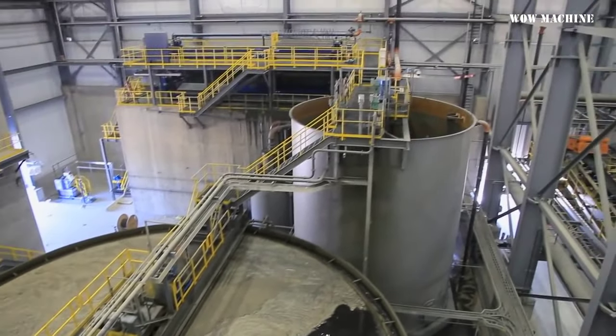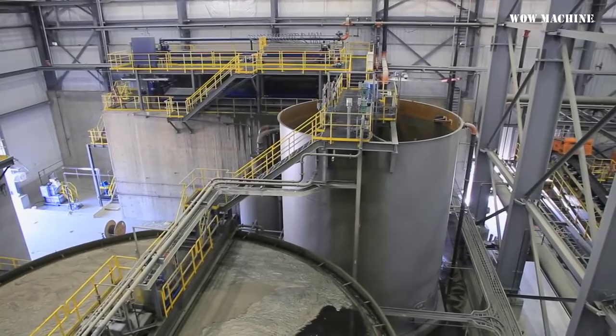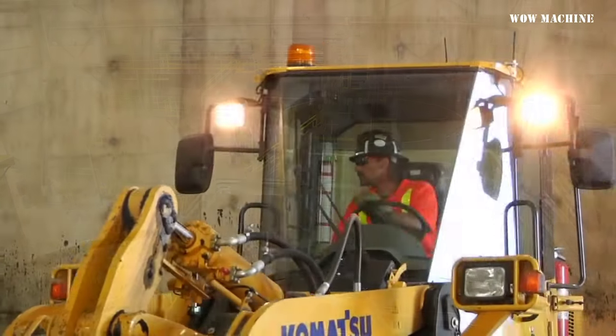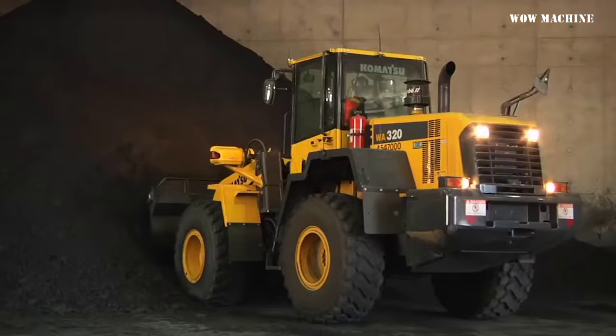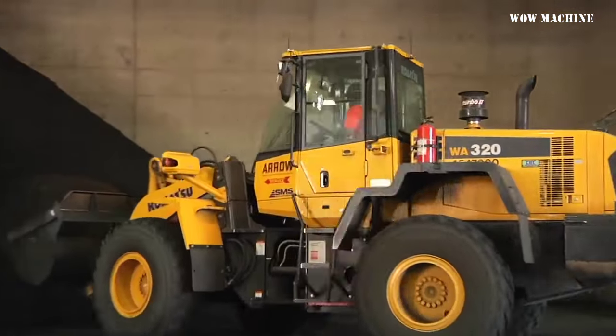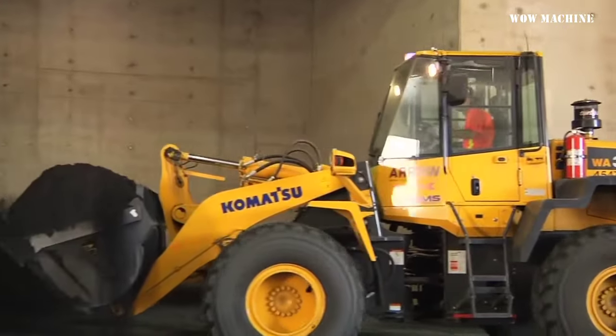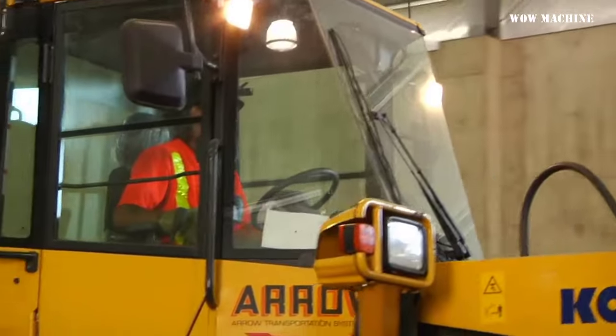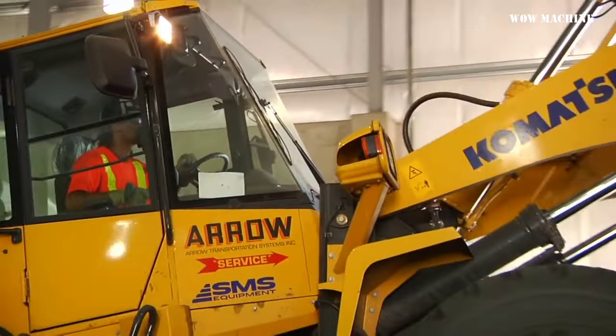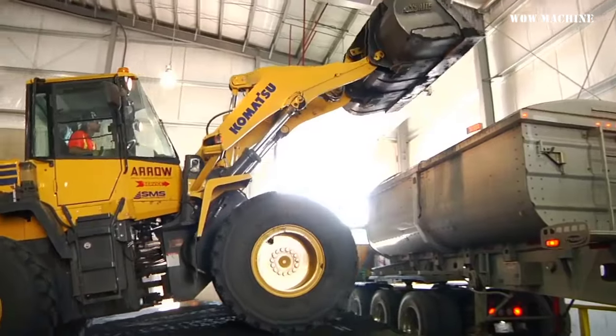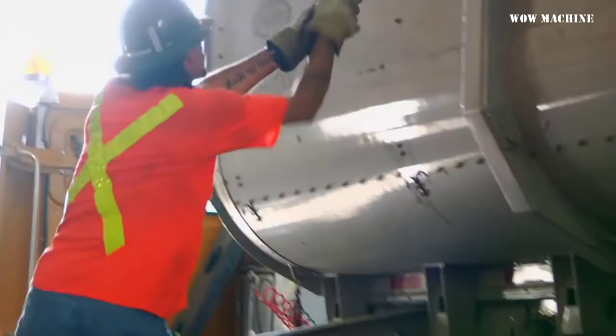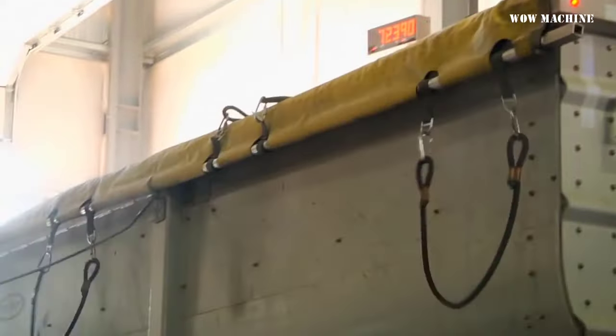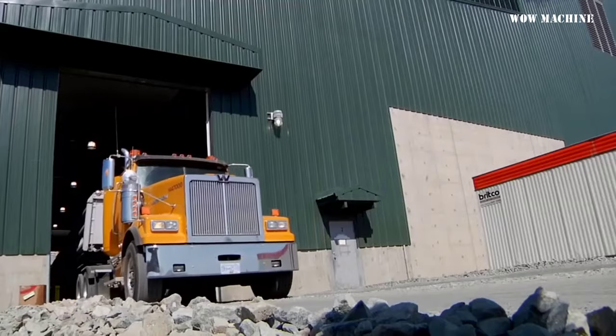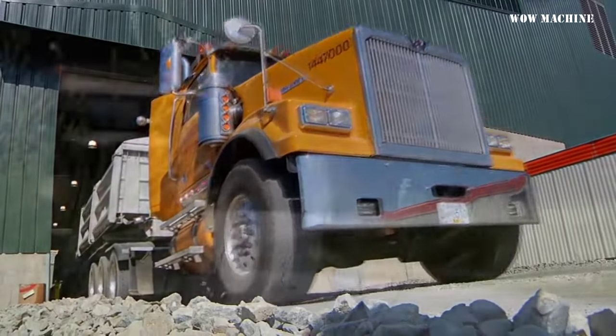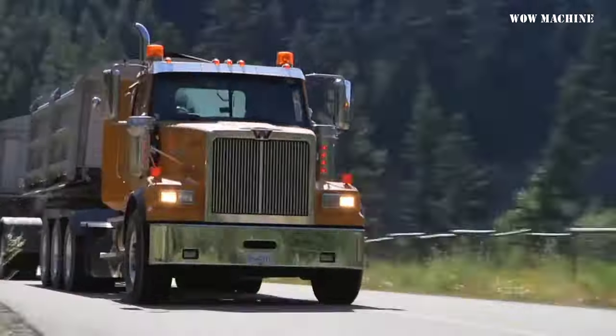The resulting concentrate, containing about 5% copper, is further refined in a regrind mill and cleaner flotation columns, producing a final concentrate with approximately 25% copper. This thickened concentrate is then filtered to reduce moisture content to around 9%, creating a product that consists of copper minerals along with small amounts of gold and silver. Copper Mountain is projected to produce approximately 175,000 tons of concentrate annually.